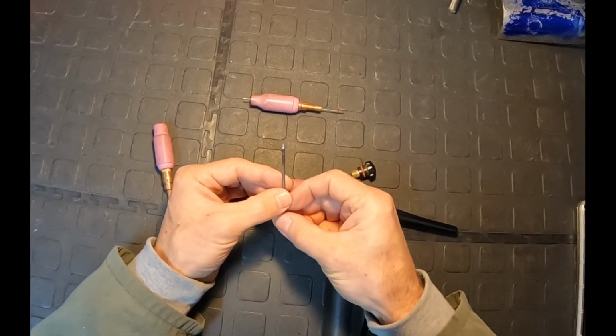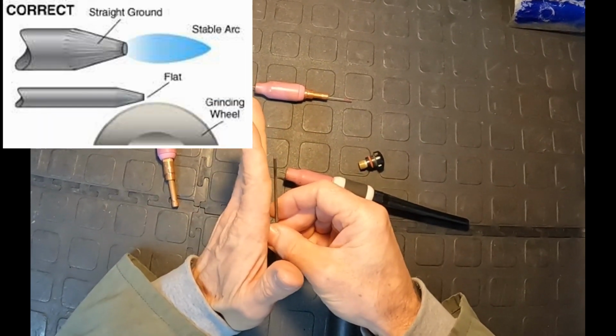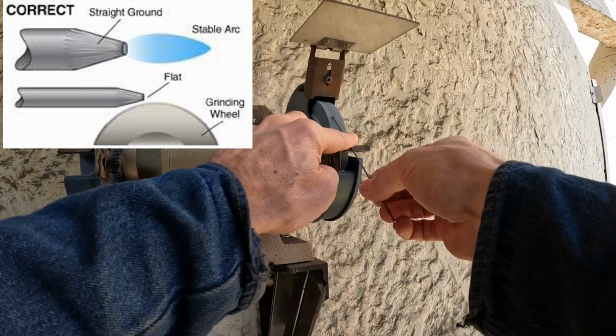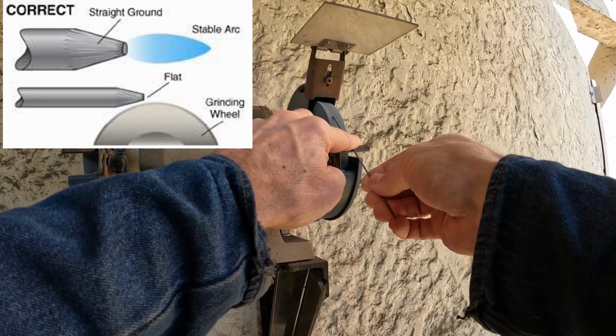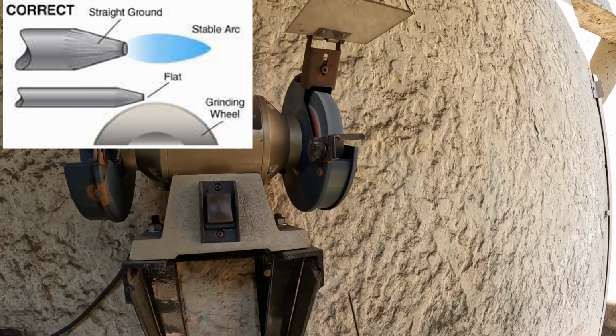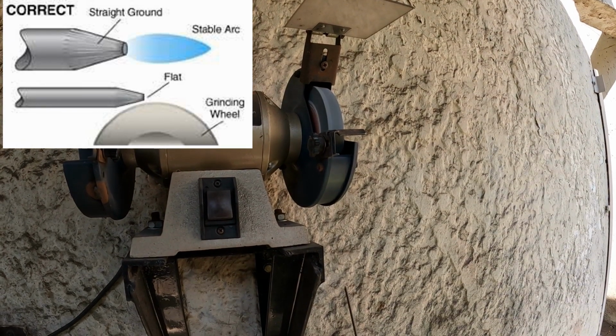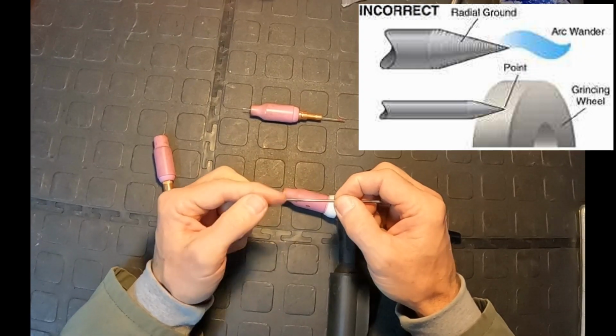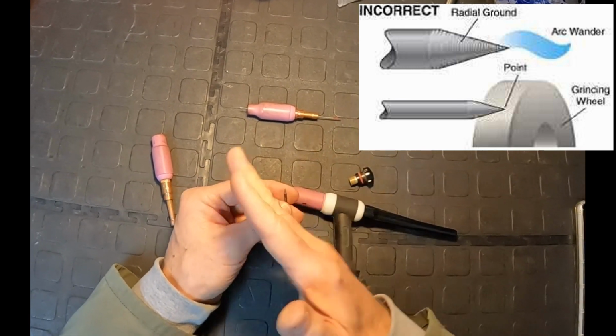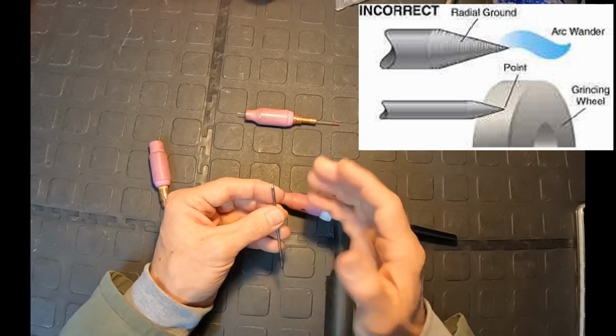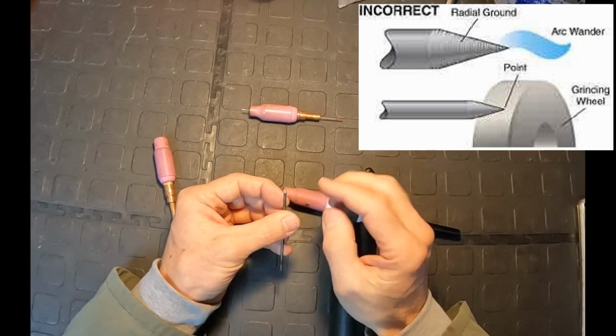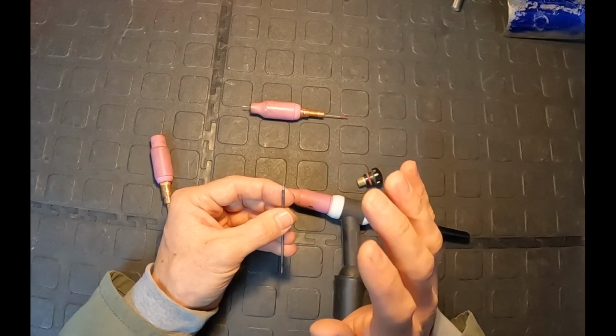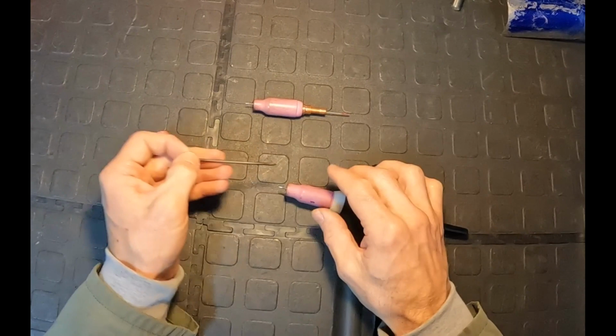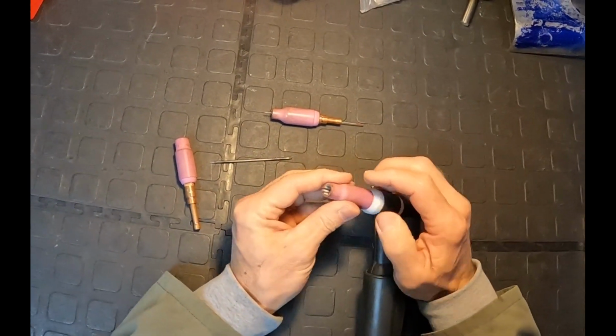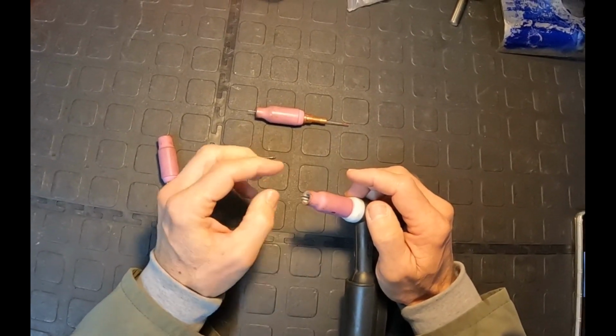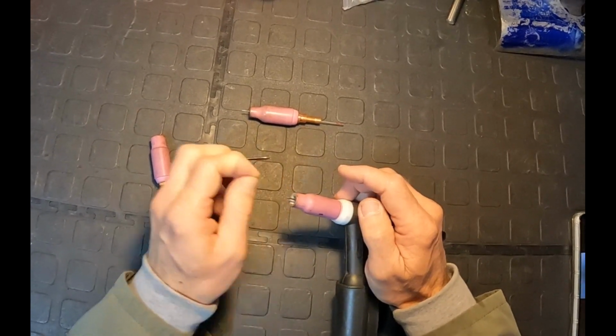When you're grinding the tungsten rod, it needs to be in the same direction as your grinding wheel. So in other words, all the grinding marks are in this direction. The reason for this is if you do it in the opposite direction, so your grinding marks are in this orientation, you end up with a very unstable arc. So if these are in the direction of your grinding wheel, your arc is stable and you won't have any issues.